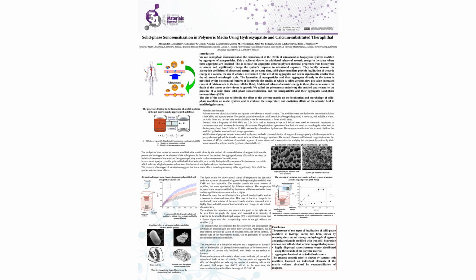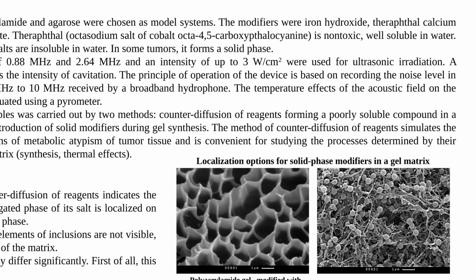Analysis of the samples modified by counter-diffusion revealed 2 distinct types of solid phase localization. In the case of theraphthal, the aggregated phase of its calcium salt was localized on individual elements of the agarose matrix. These elements act as nucleation centers for the solid phase. In contrast, in the polyacrylamide gel modified with iron hydroxide, structurally distinguishable inclusions were not observed.